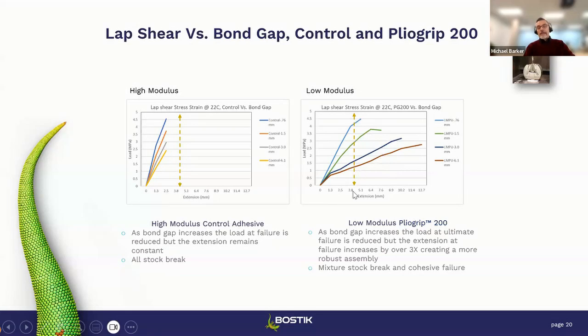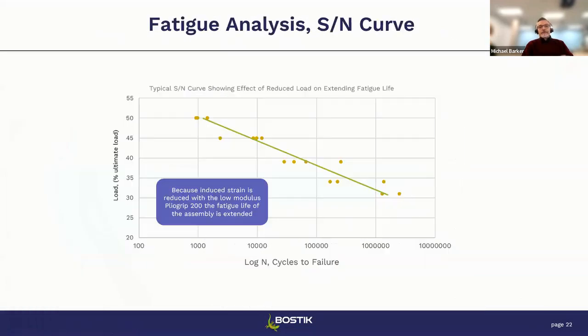So in all cases, they far exceed the 4.2 millimeters worst case expansion and contraction of that assembly. And that in itself is the true advantage of the low modulus adhesive. And so how's that going to play out? It's going to build a more robust assembly, and it's going to greatly reduce the potential for bond line read-through, which in itself allows the molder to bring out a thinner gauge substrate.